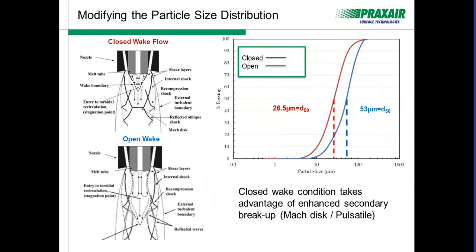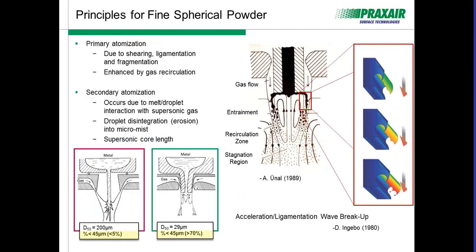Moving on to slide 6, what we'll talk about here is gas structure. And so what we showed on the previous slide, and let me just back up one slide to confirm, is when you take advantage of both of these primary and secondary atomization phenomena, you're operating what we call a close-coupled mode. Close-coupled atomization means that the gas physically is closely coupled to the liquid. So as the liquid exits, it's immediately impinged upon by the gas.